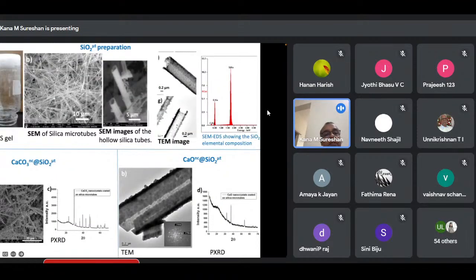So this is the real picture, actually. These are the silica fibers. After making the silica fibers, of course, you can see this is hollow once you remove the gelator. This is an SEM picture, scanning electron microscopy picture. The scale bar here is 5 micrometer, and this scale bar is 0.2 micrometer or 200 nanometer, a very, very small scale, actually. You can see this is hollow, actually. The silica gel is hollow.